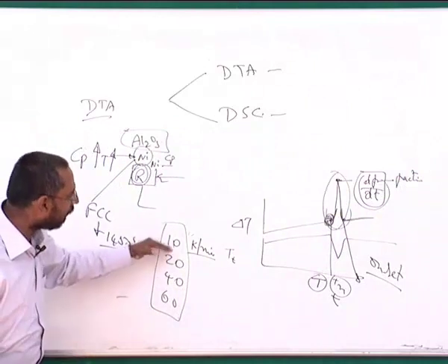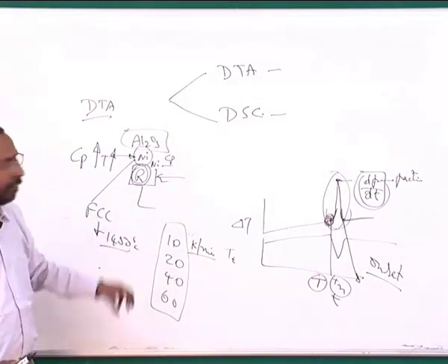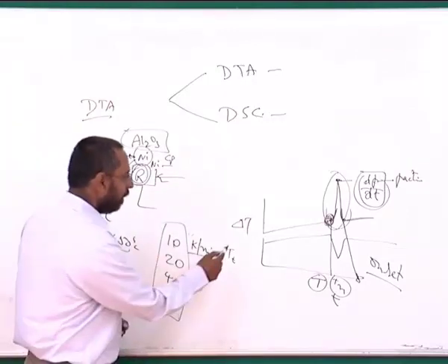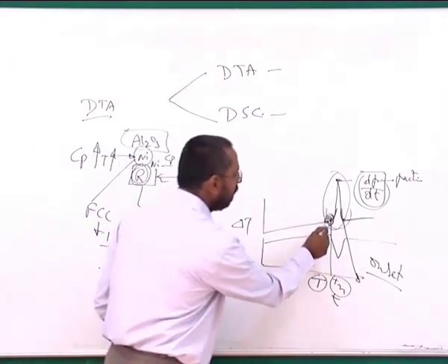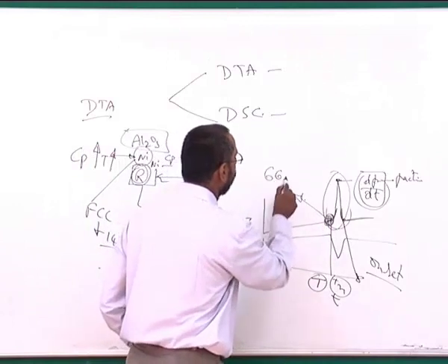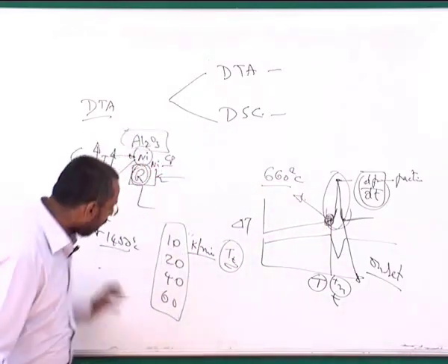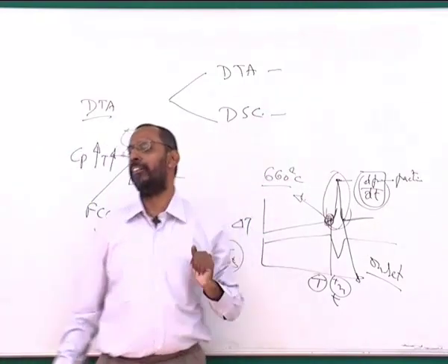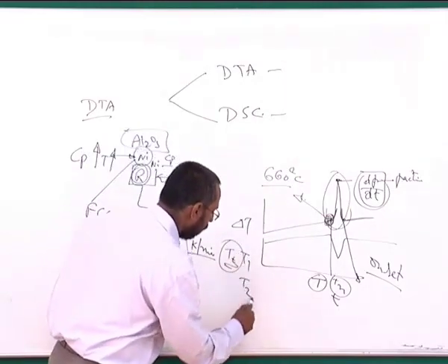So when the heating rate is close to the equilibrium heating rate, which is very close to 0, the actual transformation temperature at that heating rate is the true equilibrium transformation temperature, which is, for example for aluminum, let's say 660 degrees centigrade. If I am heating it faster, it will not be 660, but it will be higher than 660. And if I measure all these, let's say T1, T2, T3, T4,